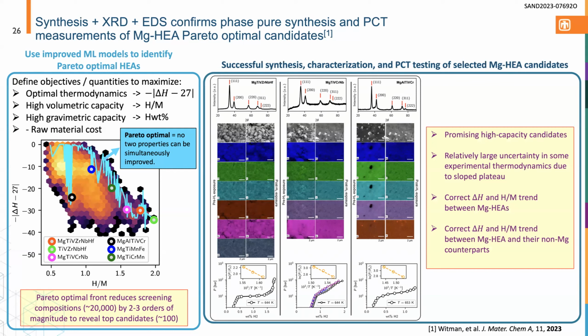We decided to focus on magnesium high entropy alloys just because magnesium in and of itself is an interesting hydrogen storage material, but it's interesting to see how it behaves when it's alloyed in a high entropy alloy. So we targeted new materials. We generated promising high capacity candidates. And we got the correct trend as predicted by machine learning between delta H and hydrogen to metal ratios, and the correct trend between the magnesium high-entropy alloys and their non-magnesium containing counterparts. But unfortunately, these ones are basically on that right side of that plot, so their delta H's are still too high to be practical for real-world hydrogen storage. So we've got to essentially move to the left on that Pareto front in the next round of materials.